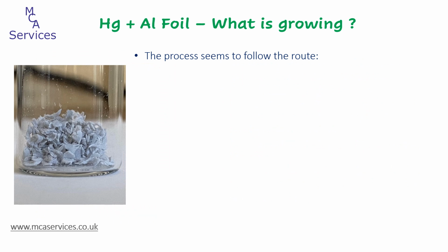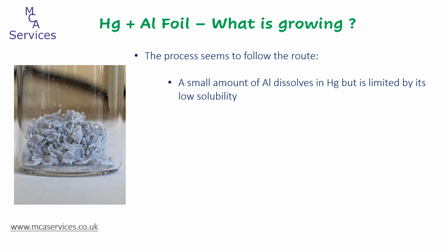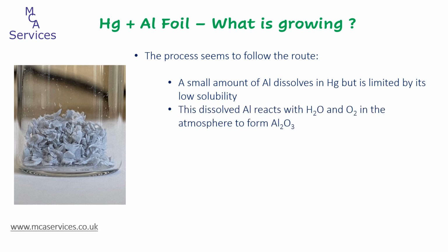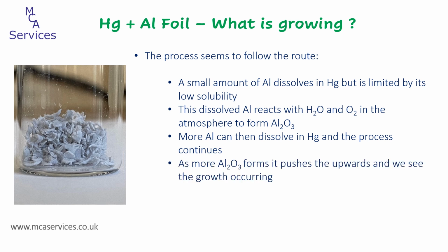So the process seems to be, as mercury contacts the pure aluminium, amalgamation starts, but this is limited by the low solubility of aluminium in mercury. The aluminium dissolved in the mercury then reacts with oxygen in the atmosphere to form aluminium oxide. It's not entirely clear, but this may also require water vapour to get it started. As the dissolved aluminium forms the oxide, more aluminium from the foil can then become dissolved or amalgamate with the mercury. And the process of dissolution followed by oxidation continues, and the oxide growth continues, pushing upwards from the aluminium surface, as we can just see in that video. So the off-white fluffy material is aluminium oxide.